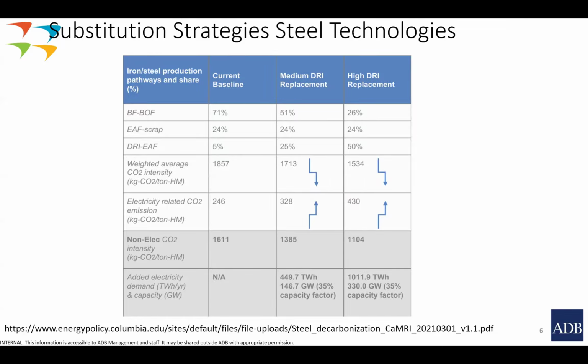In the medium term, when the end of lifetime comes up, if we can shift the blast furnace process from 71% to 51%, scrap remaining the same at around 24% because of availability of scrap, and the DRI-EAF route increases from 5% to 25%, then we will be able to reduce from 1.857 tons of CO2 per ton of steel to 1.713.